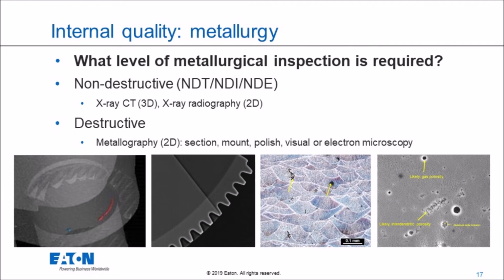And in terms of destructive testing, the standard process is you take your part, cut it up, mount it, polish it, and then etch it, and you can look at the melt pools and the pores, and that's fantastic. But how can you be sure that the slice of the part you're getting is representative of the whole part, or that you're catching pores in critical locations? You can do a similar thing with electron microscopy or visual microscopy.